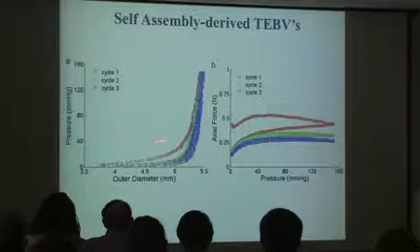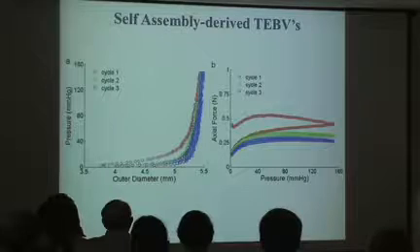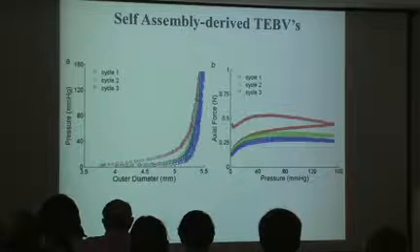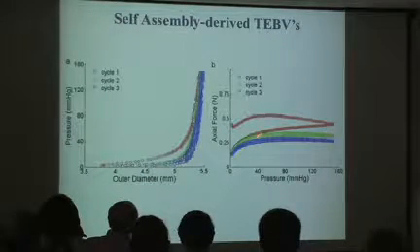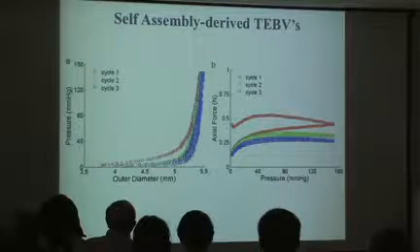Unlike the collagen gels that we showed earlier, when we load and unload these vessels, we get repeated cycles even over supraphysiologic pressures. And so these don't creep, they don't relax like we saw the collagen gels do. This is the axial force during those loads, and this is a typical response that we see even from native arteries, that there's a little bit of a relaxation in the axial force. So these look pretty good, right?